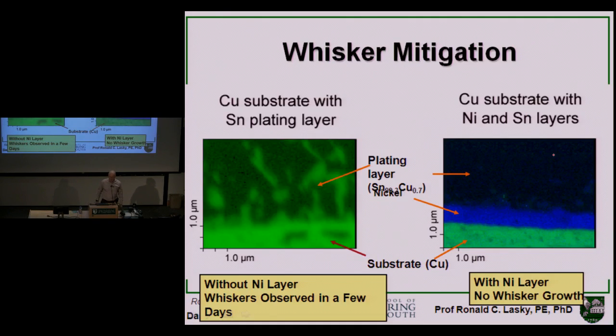This is an electron micrograph to show how much of the copper can diffuse into the tin. This is the copper is green here, and when we put a nickel layer over it, the nickel being blue, you can see that there's very little up here. This is essentially all tin. So taking action like this minimizes the effect of tin whiskers.